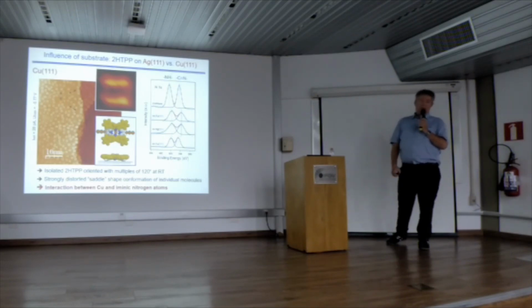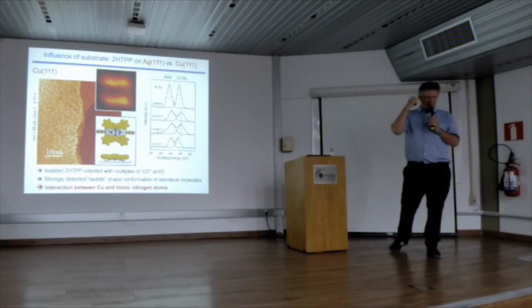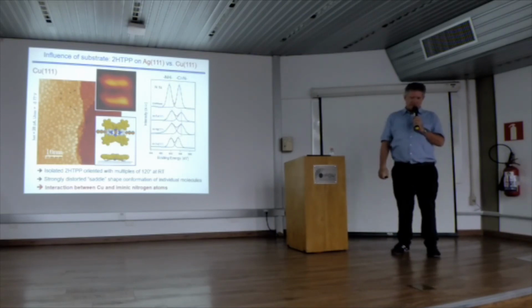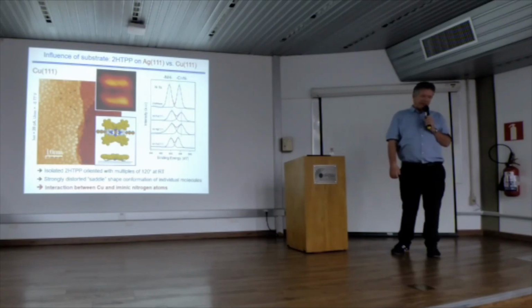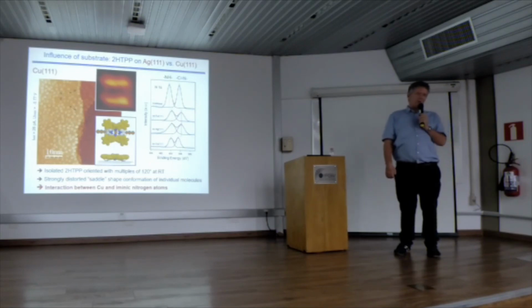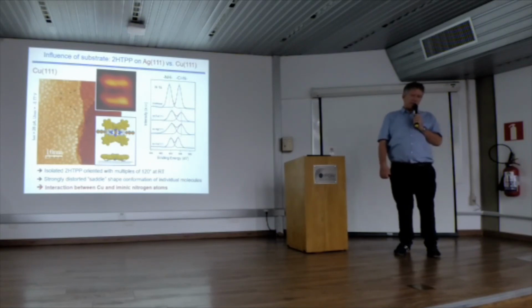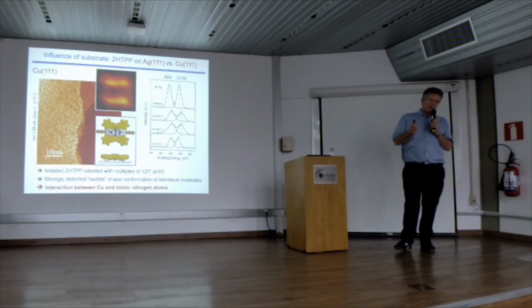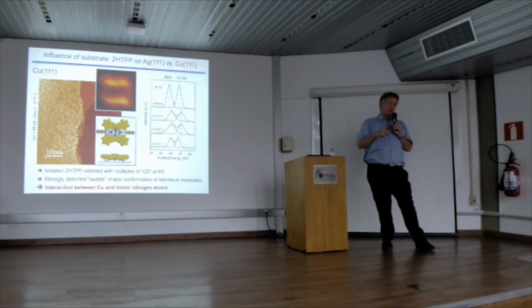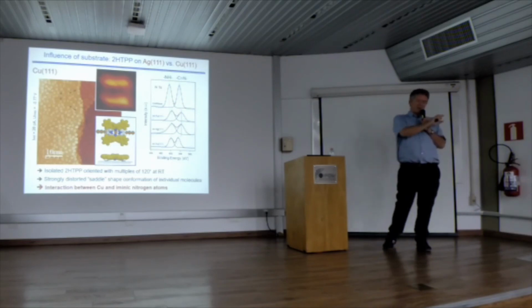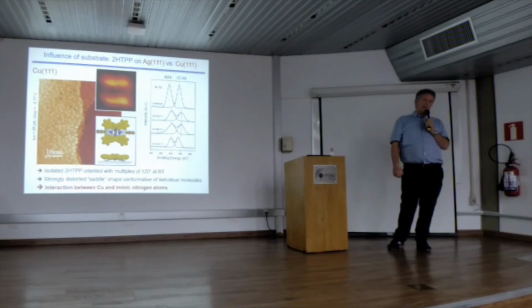Good question, I have no answer. What you can do, which has been shown on magnesium oxide very nicely by the group of Martin Sterrer in Graz, is tune the interaction by changing the work function of the substrate. On certain oxide surfaces, there's a little oxygen deficiency or oxygen excess, and you can change the work function quite significantly. Also if you have a metal, then an oxide layer, and on top of that the porphyrins, you can modify the chemistry.